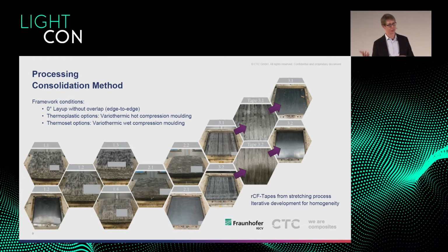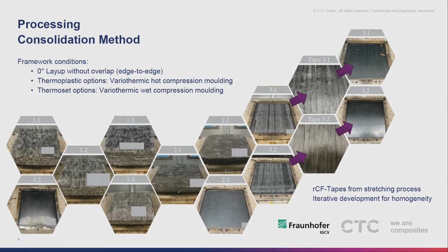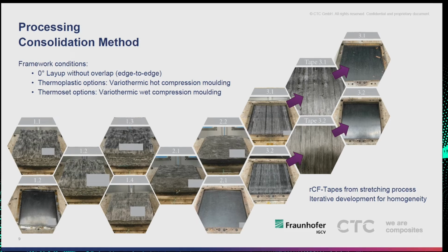And through a couple of iterations with these partners, and maybe you can see it with the images we have here, the very first iterations of material were a non-woven with a slight alignment. It was a mess of a material, and we couldn't actually call it a UD. This was based on the carded wide width textile, which is just a combed non-woven. And we pretty quickly found that this doesn't work for us. And through some iterations, the most promising technologies that we saw, just by practically looking at the quality of the textile in front of you, were those working with slivers and subsequent alignment. They are much better for us in terms of the quality of the component that we produce.